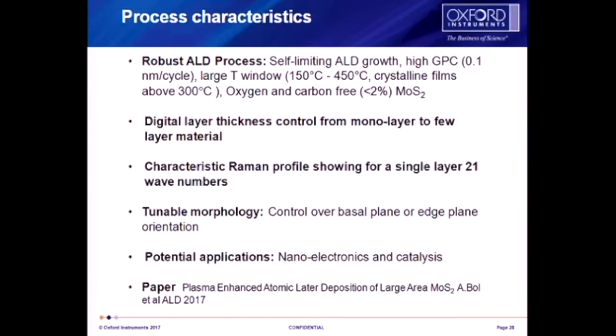They reported a very robust ALD process, which is self-limiting, with a high growth per cycle of around 0.1 nanometers per cycle, with a large temperature window. As I said, crystalline films above 300 degrees C, with very low carbon and oxygen content. Because it's ALD, you've got real good control of the monolayer thickness, so you've got very uniform material. You see the characteristic Raman profile, with about 21 wave numbers between the two peaks.